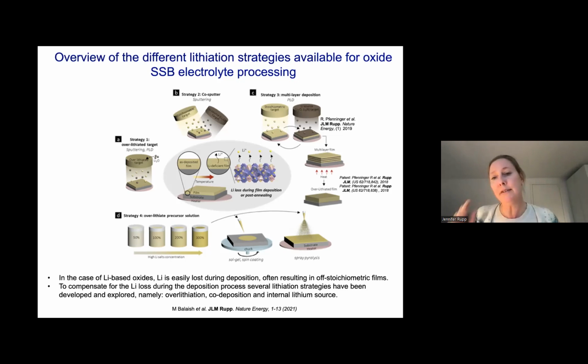Now, turning to thin films, this is really tricky, because if you were to take a very over-lithiated pellet of lithium garnet, for instance, a good conductor, and use an ablation technique like pulsed laser deposition, which is just a laser shooting on the ceramic target, when the material comes down, you form a film. Then you lose, because of the high energy, most of the lithium on the way, and you get very under-lithiated films. And it was, I think, only up to our paper where we could show how to circumvent the lithium loss problem with a trick.